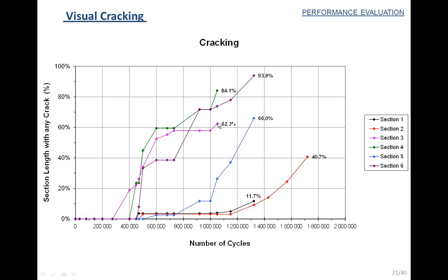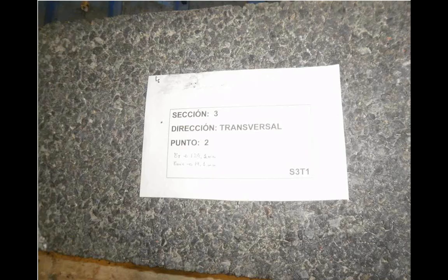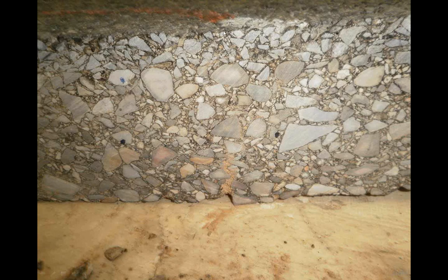In fact, at cycle 1,050,000 we had to repaint the section, so we took some slabs from the asphalt layer. And this is, for example, one of the slabs. This is a transverse slab. So we saw that there was bottom-up cracking. You can see here the crack, and in this case the crack was also visible on the surface.